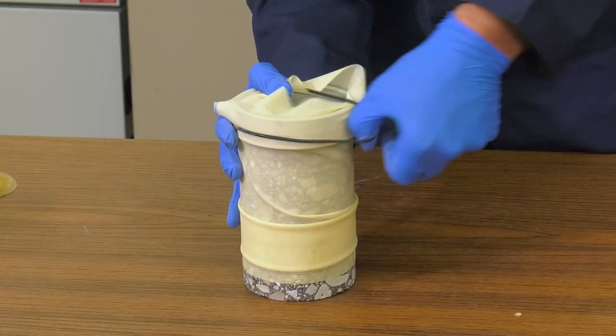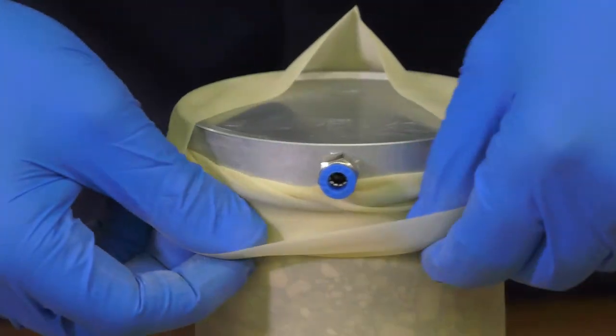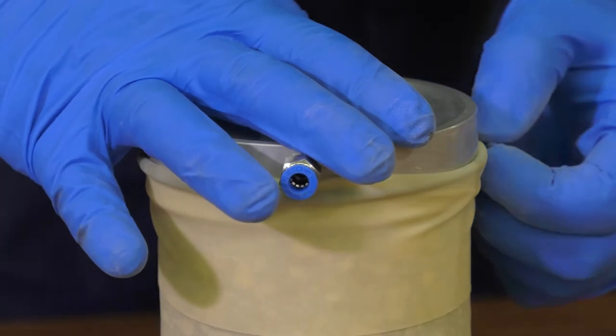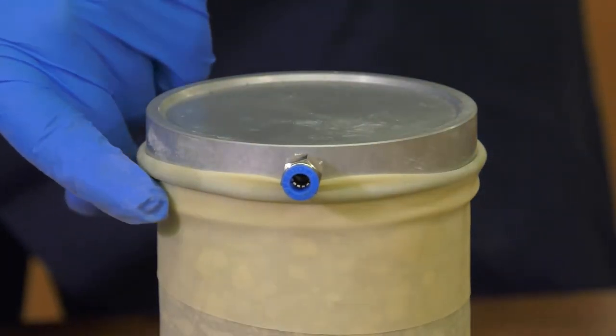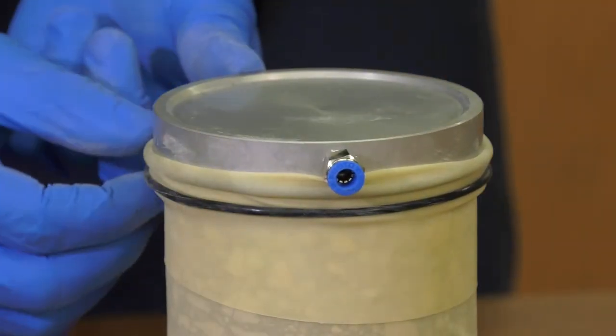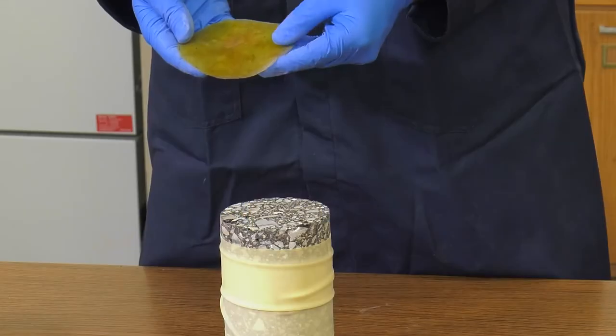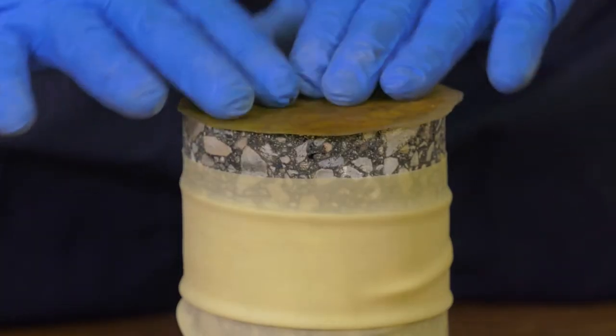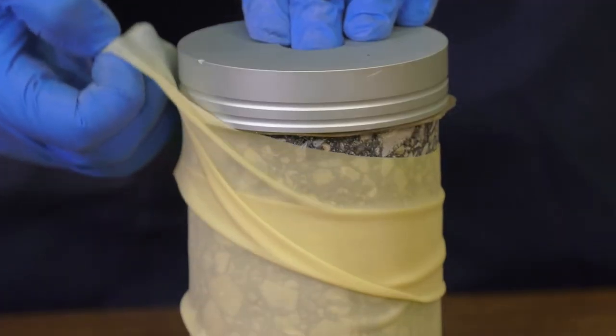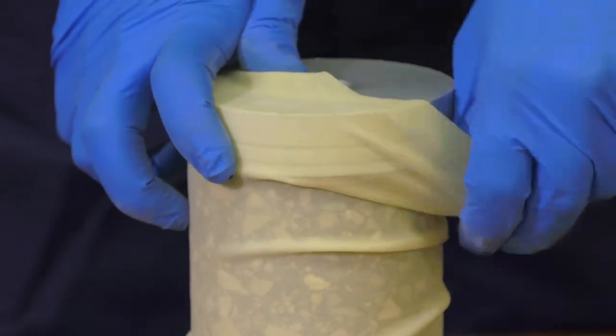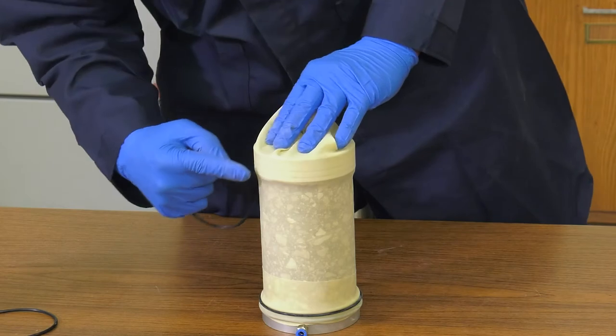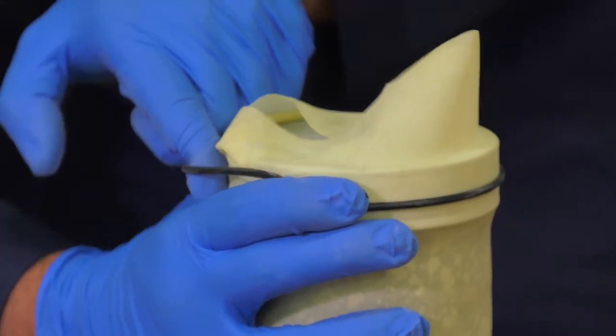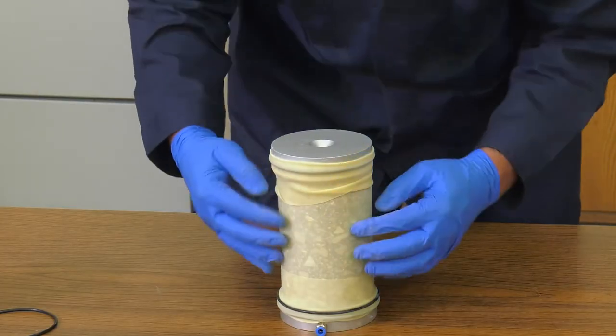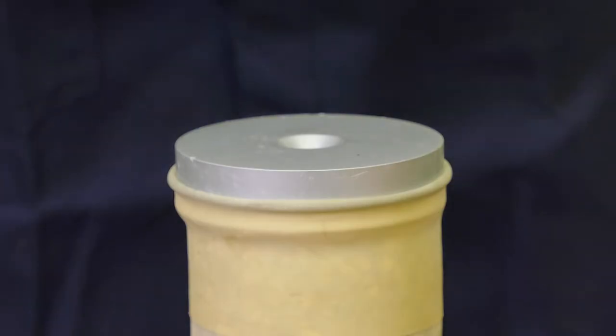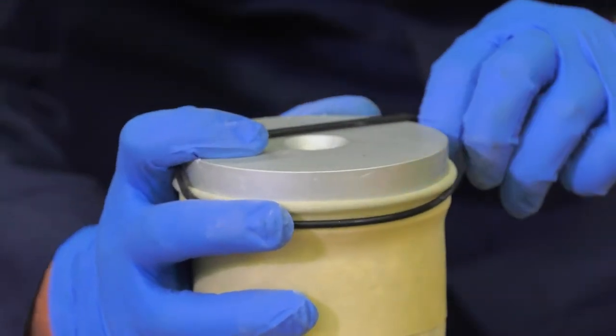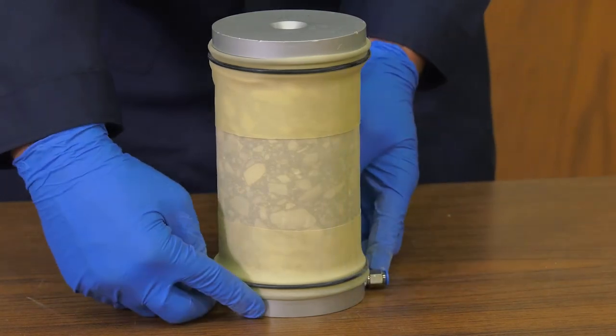Secure one O-ring around the top groove of the platen. Next, flip the membrane down evenly to reveal the platen and straighten. Secure another O-ring on the second groove. Take the circular latex membrane prepared for the upper platen and place on top of the specimen. Position the upper platen on top of the specimen and pull the membrane up and over the platen. Place an O-ring on the top groove and then fold the membrane down and straighten. Attach an O-ring to the second groove. The specimen assembly is ready for conditioning.